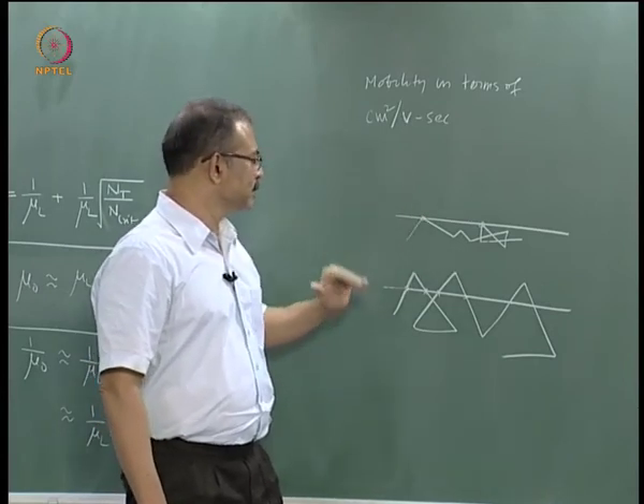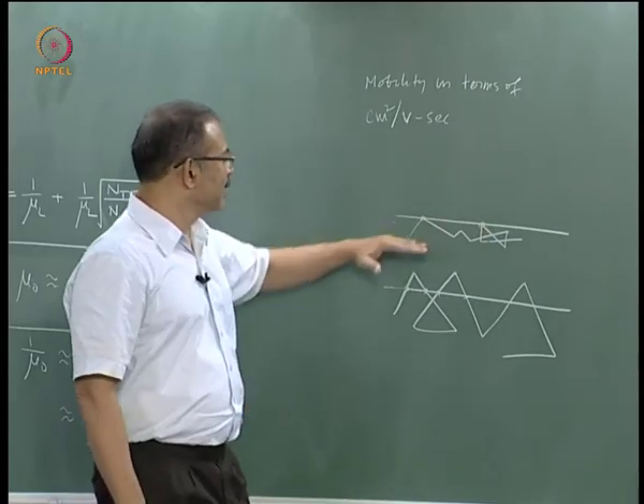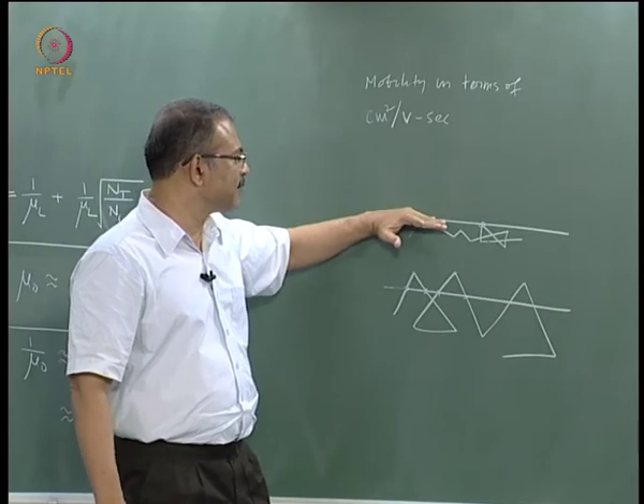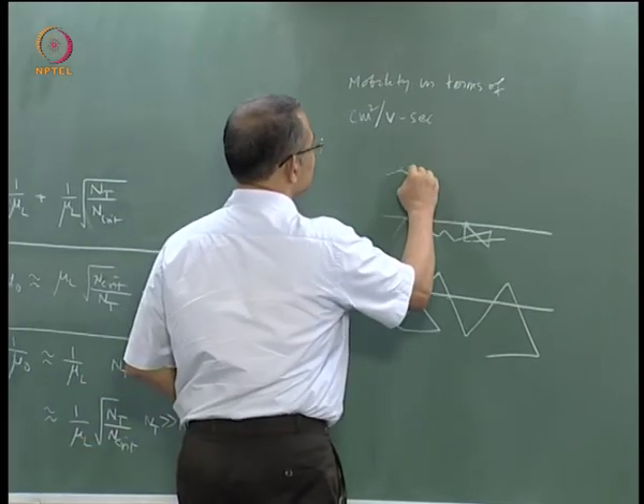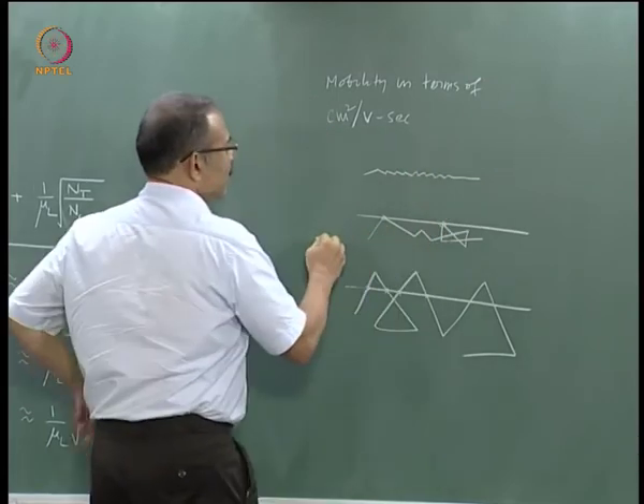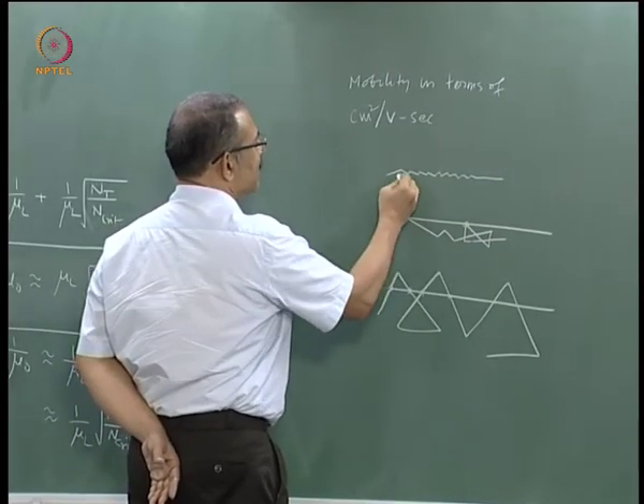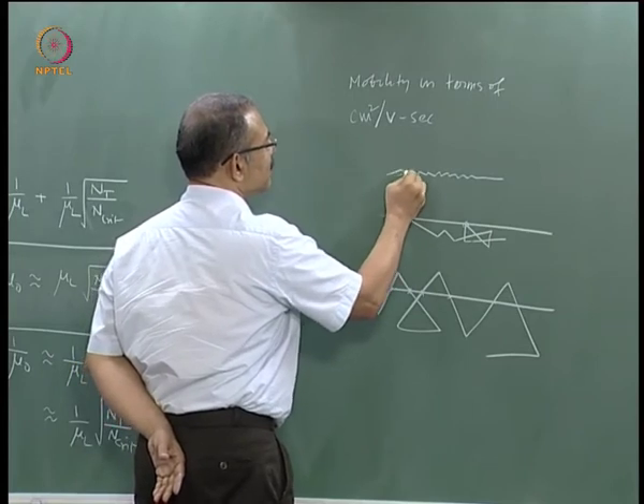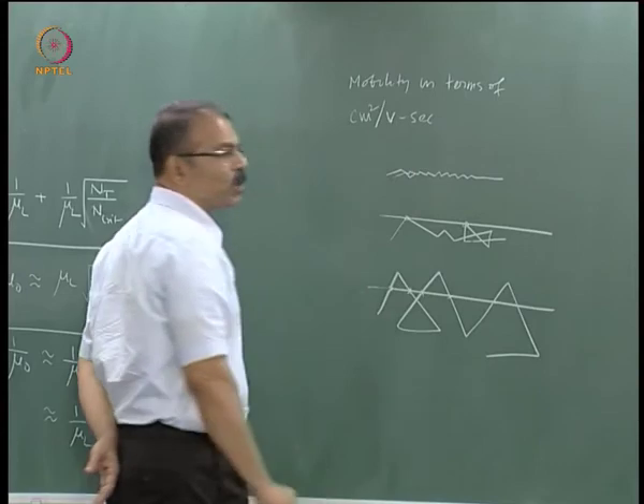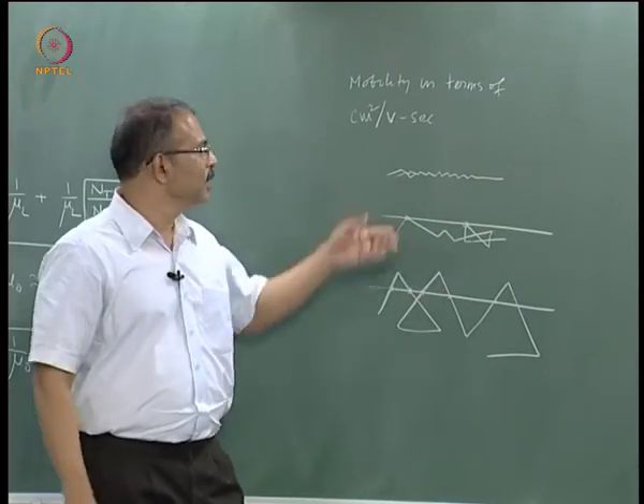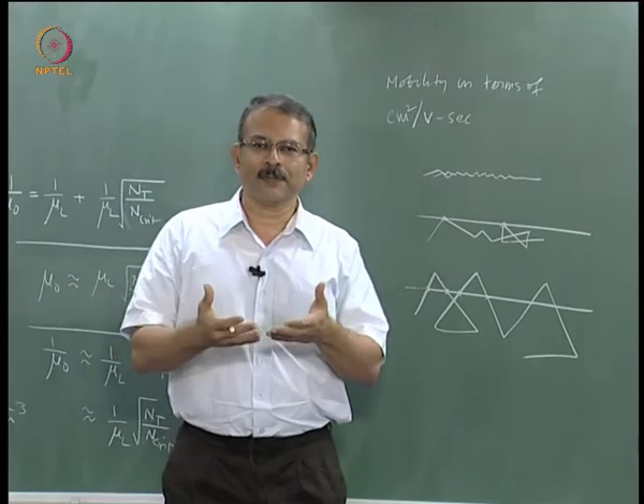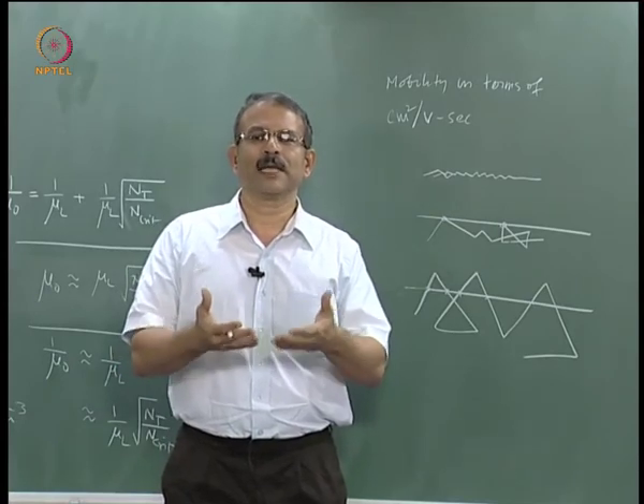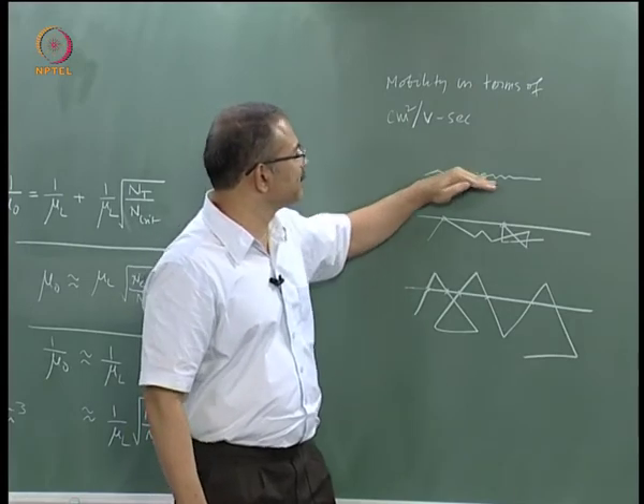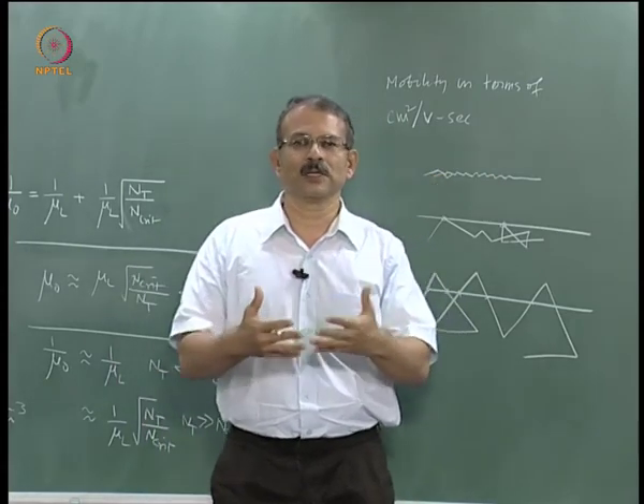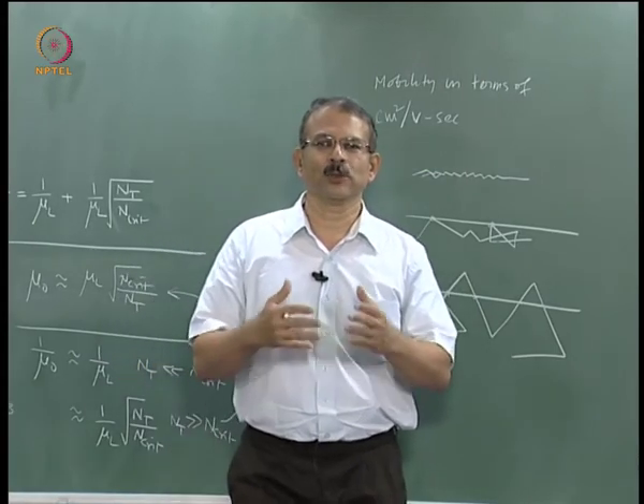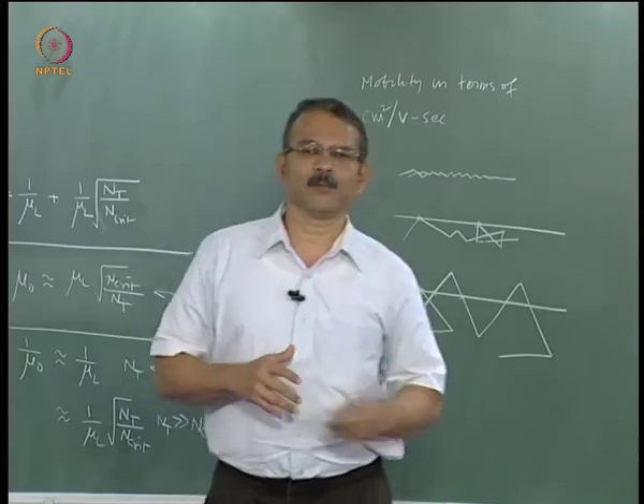Now, in addition to these, I have shown the surface to be flat. At atomic levels, it is not that flat. So, the picture of the surface is actually something like this. Now, you can easily appreciate that the number of scattering mechanisms would be more if the surface is rough, because the surface area is now much more than what you can get with a flat surface. Another way of looking at the scattering because of roughness is to regard it as something like a friction. If you are moving against a rough surface, you know that the resistance from the surface is more, the friction is more. So, the surface roughness scattering can also be viewed as a friction kind of effect.